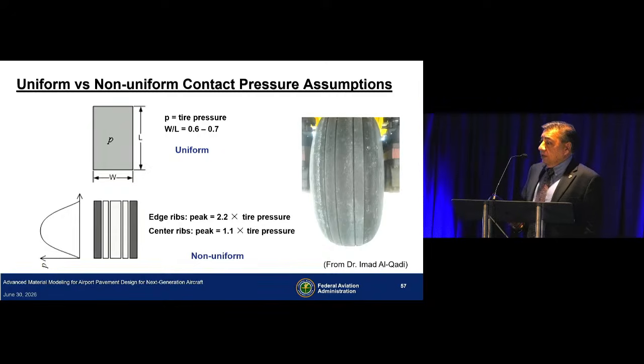Another thing to look at is the non-uniform contact pressure distribution under the tire. And this slide I took from Professor Al-Qadi. One of the things that you see here is they found that at the edge ribs, the peak pressure is about 2.2 times the tire inflation pressure. And in the center ribs, it's about 10% higher than the inflation pressure. And to me, that could be the reason why we see longitudinal cracks develop right along the tire edges. And this is something that happens every single time.